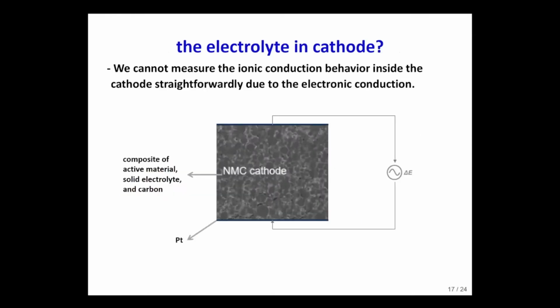Okay, so we determined the resistance of the electrolyte layer and the charge transfer resistance at the anode. So the next one was the charge transfer resistance. Actually, the next one was the cathode. The cathode is electronically conductive. It contains a conductive agent, and the cathode active material itself is conductive. So we cannot get the information inside the cathode with this simple configuration.